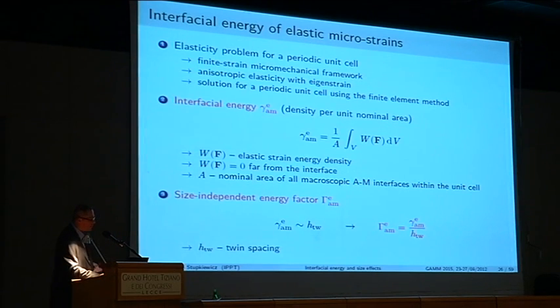So how to do that in practice? Consider an austenite twinned martensite interface. We formulate an elasticity problem for a kind of periodic unit cell. I will show it in a second. We use a finite strain micromechanical framework. We consider fully elastic anisotropy and eigenstrains related to transformation strains. And then we solve the corresponding problem using the finite element method. Once we solve the problem, we can determine the energy.